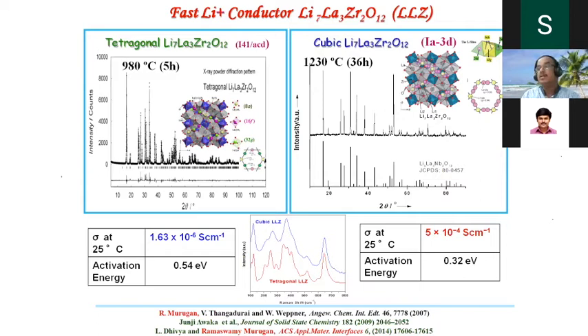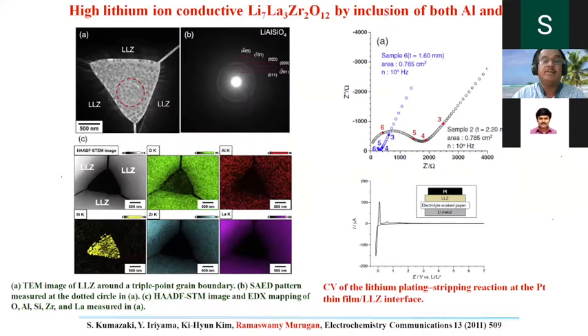That's the reason for the incorporation of the aluminum and reducing the lithium concentration very close to 6.6. When it changes phase from tetragonal to cubic, then I could improve the conductivity. I used to get 10 power minus 4. But others, unable to incorporate the aluminum and unable to reduce the lithium concentration, end up with this tetragonal structure. This is how, in 2010, we realized that everybody understood the mechanisms.